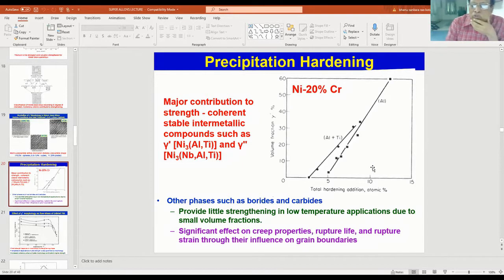There are several other phases I said, carbides and borides. They provide little strengthening in low temperature applications due to small volume fractions. There will be 1%, 1.5%, 2%, it will not exceed. Whereas gamma prime can be up to 70%, 80%. It varies from 10%, 15%, depending upon the amount of the alloying elements that you have added.